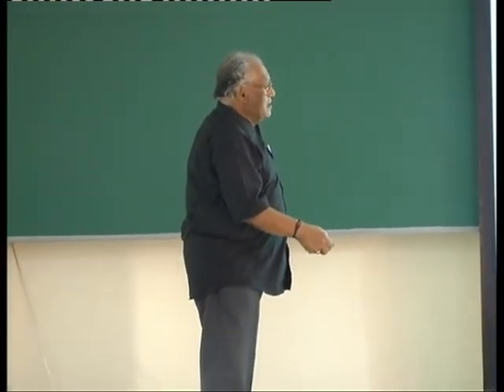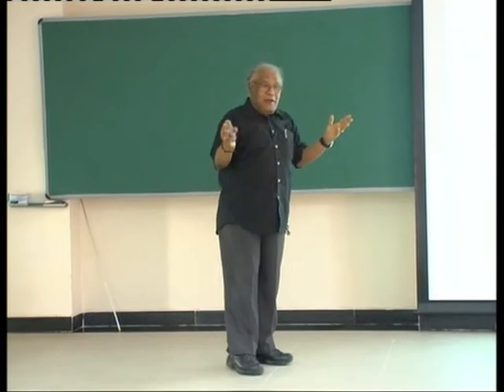So why do we want FeMn? Why not put FeCr? So we put FeCr, and they also show ferroelectricity around the same temperature as the magnetic transition temperature. And you can see very large magnetocapacitance at that temperature. There is a slight dielectric anomaly at the transition. So what I'm showing is, you see, multiferroic and magnetoelectric is not such a great thing anymore.